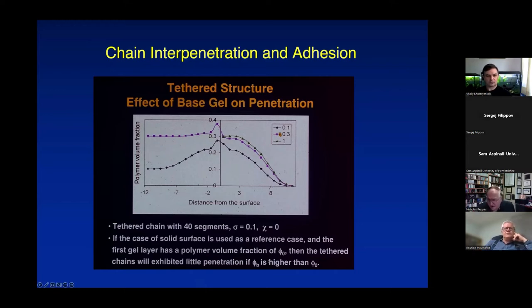The chi factor is zero. Zero is a rather good compatibility, it means compatible. You don't have to worry about it. So we start looking now at the interactions on that surface, for different conditions. Here's the distance from the surface. Look at this. Here is the chain that is inside, and this is the portion of the chain that is outside. And we see the polymer volume fraction. So we can clearly see under what conditions this chain will contribute to adhesion.